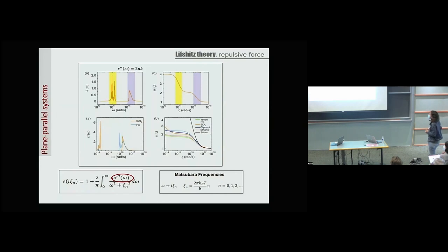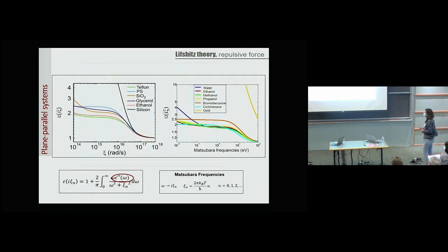And now you need to make some library of materials that can interest you, because you can handle them easily in the lab. They are chemically stable, or stable in time, and so on. And this is what we did. We made some libraries. We analyzed polystyrene, silica, or Teflon, and a lot of alcohols that we then didn't take into account because they evaporate very easily. And then we have to find some sets of materials that will give this repulsive force.